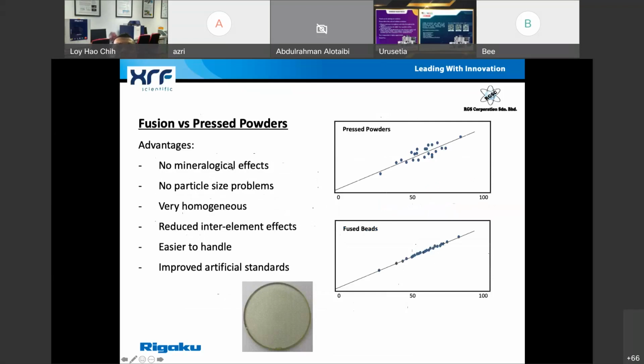Well, now the advantages of fusion. Okay. In the fusion process, because we are melting the samples into a lithium borate flux, in the melting process we actually destroy all the mineralogical effects. So there's no longer a mineralogical effect. And since everything is already dissolved and melted inside the flux, there's no longer a particle size problem. And since everything is already digested and melted, the sample is very homogeneous. Also we can reduce the inter-element effects, because the sample becomes a minority and the majority of the bead will be lithium borate. So there are very low inter-element effects and it's very easy to handle. And because this bead is a solid piece, it will not drop into powders and it will not easily contaminate your XRF.